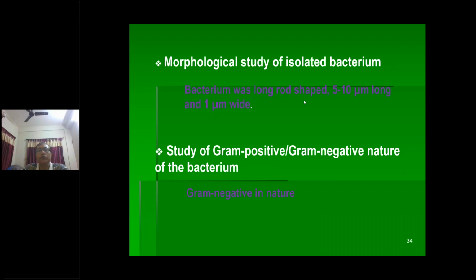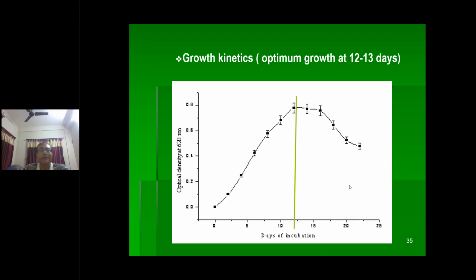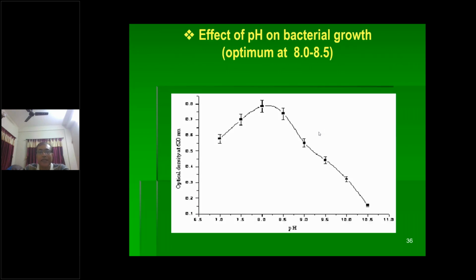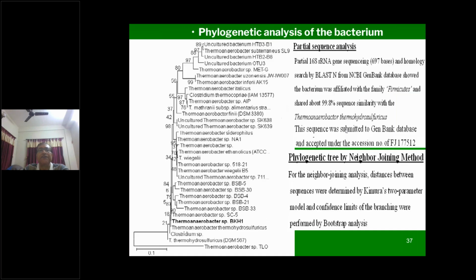This bacterium, as I already told you, is a long rod, 5 to 10 micrometers long and 1 micrometer wide. It is gram negative in nature. We have also noticed the growth kinetics: mostly at 10 to 12 to 13 days, at this age, we are getting the maximum density. That means the growth is maximum in this range. Similarly, at a pH in the range of 8 to 8.5, we are getting the maximum growth of this bacteria. And finally, the phylogenetic analysis of this bacterium has been done.